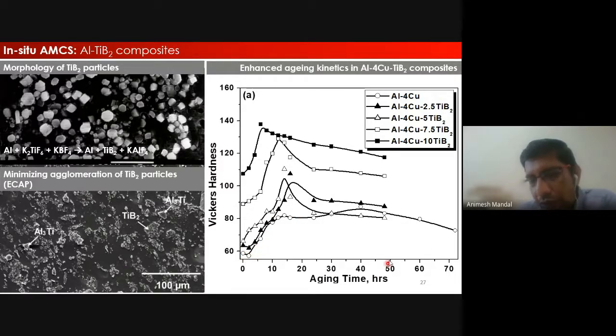As you are aging, if you are aware of heat treatment, that means heating at a certain temperature, you can see you attain a maximum hardness and then a drop. This maximum hardness we call the peak hardness. Here the time taken for peak aging is almost close to 40 hours, right? But when you add particles like titanium diboride, hardness, of course, is expected to increase, but not only that, the time taken to reach this peak hardness comes very close to around 10 hours or 8 hours.